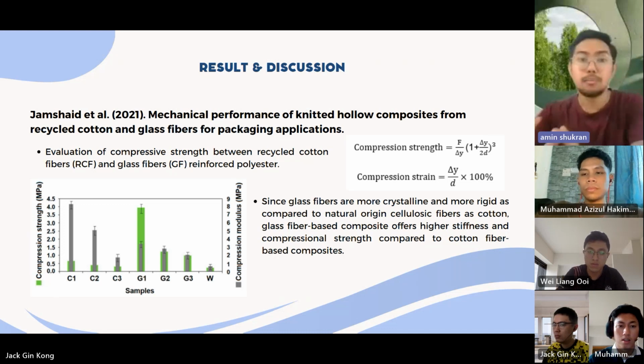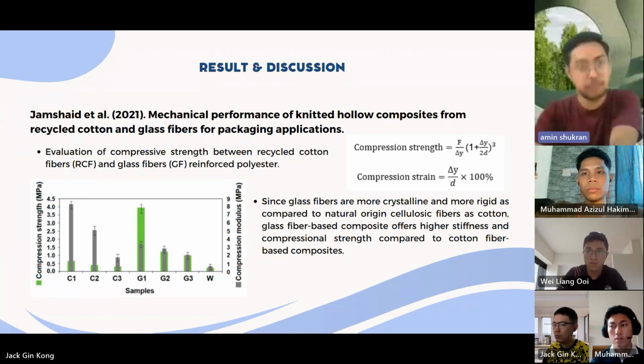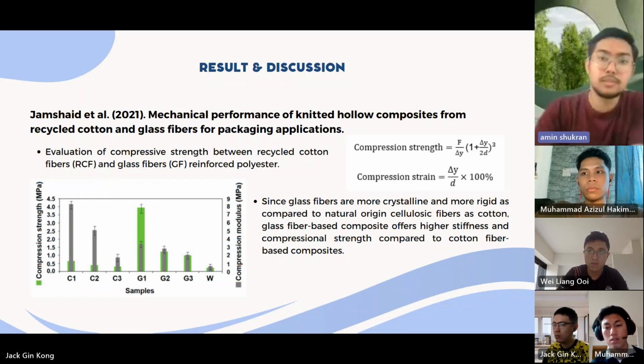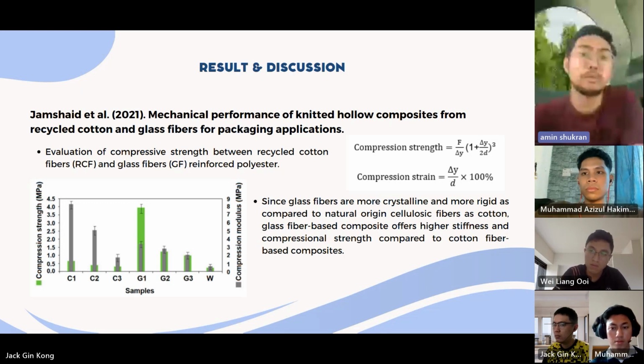However, it is important to note that the glass fiber-based composite samples are developed with higher fiber volume fraction at 50% as compared to RCF-based composite samples at only 40%. Thus, the fiber mechanical properties and the fiber volume fraction have significant influence on the overall composite mechanical performance. Then I will pass to my friend AZIZUL.